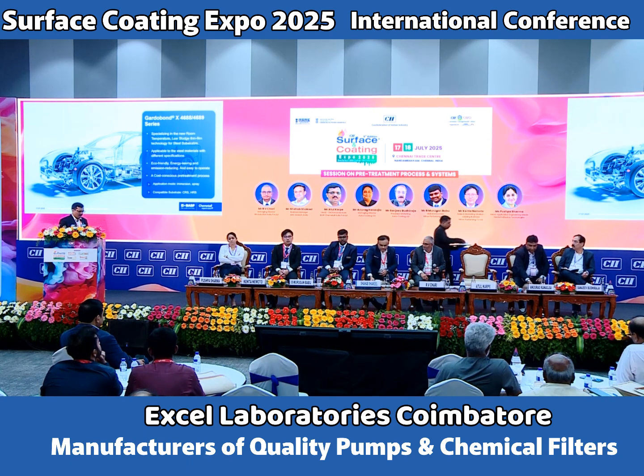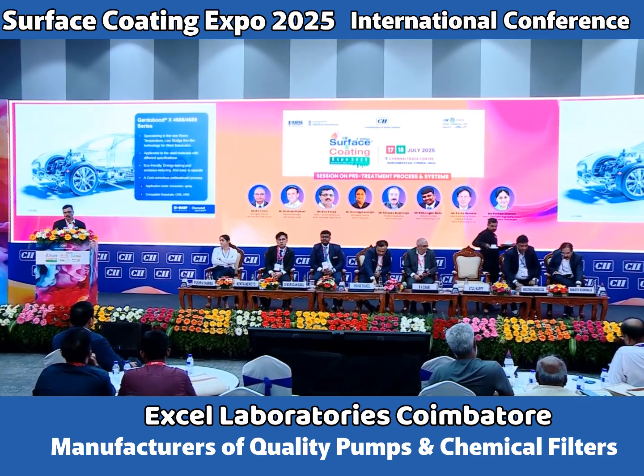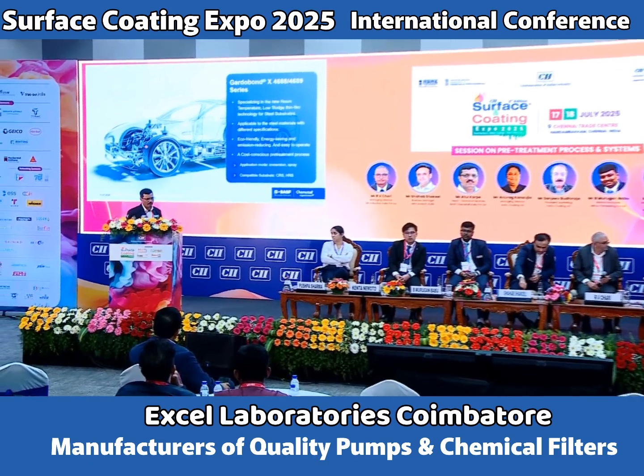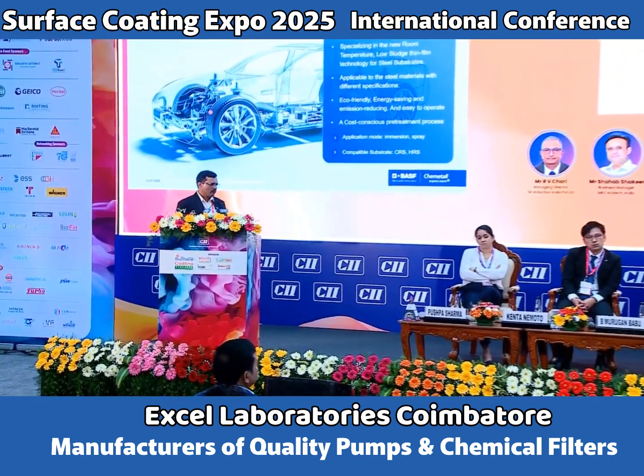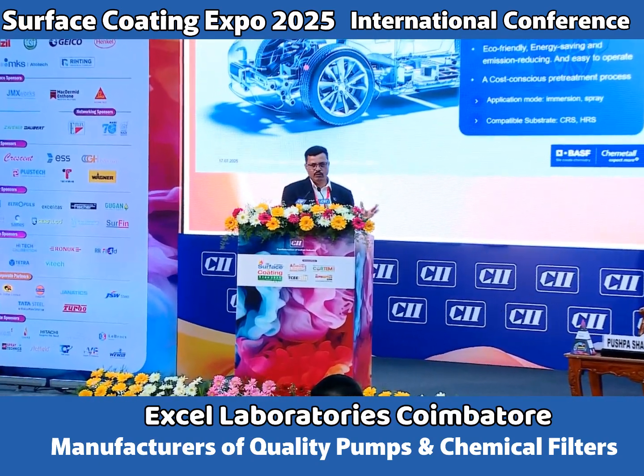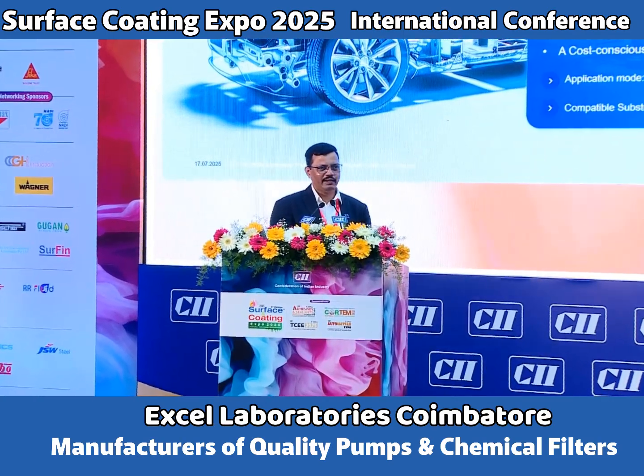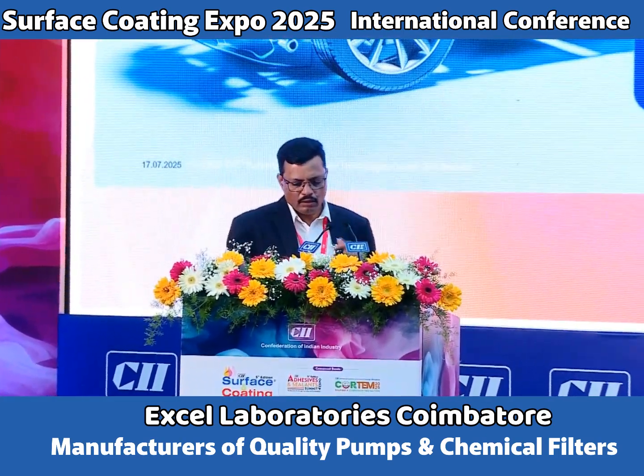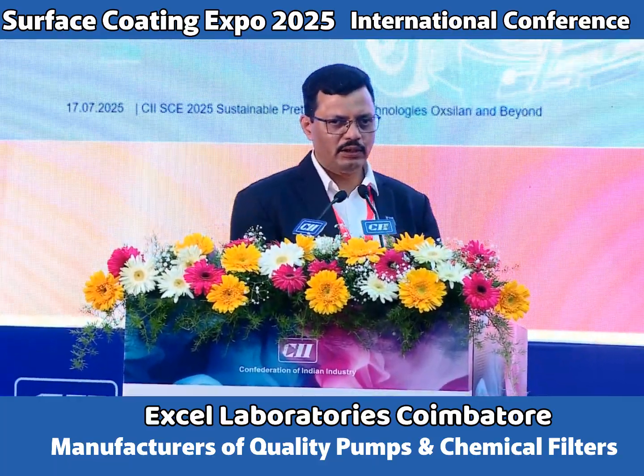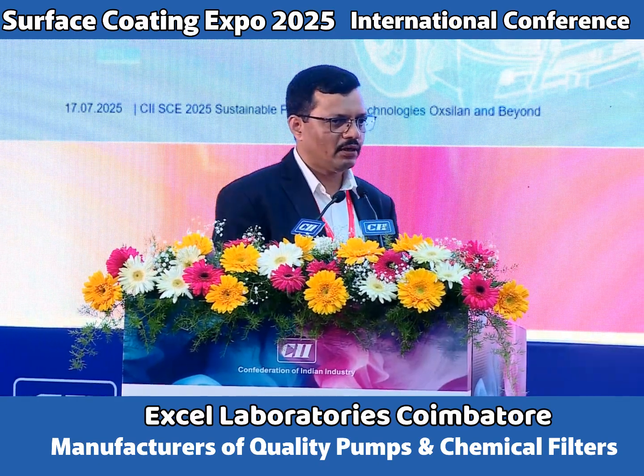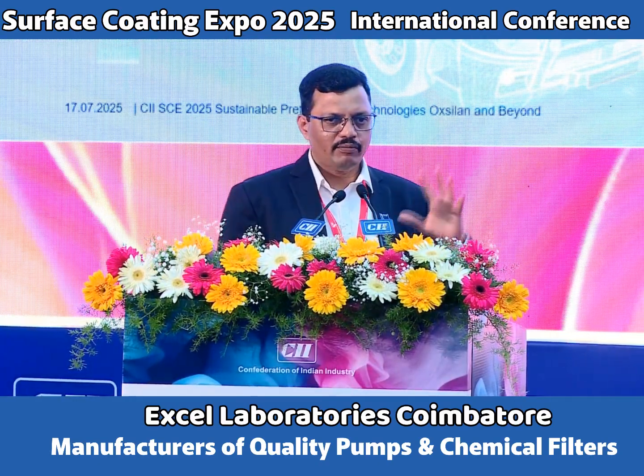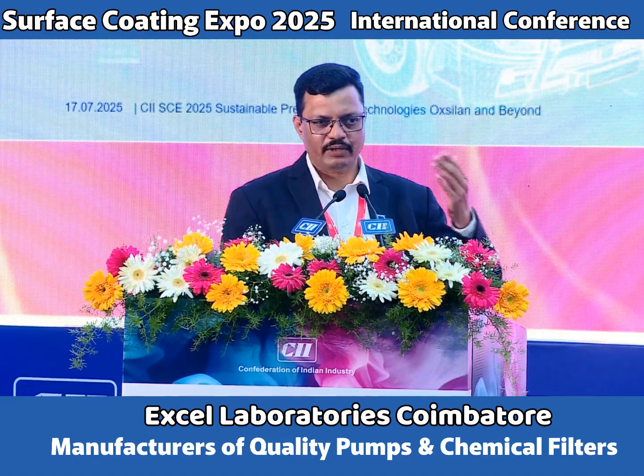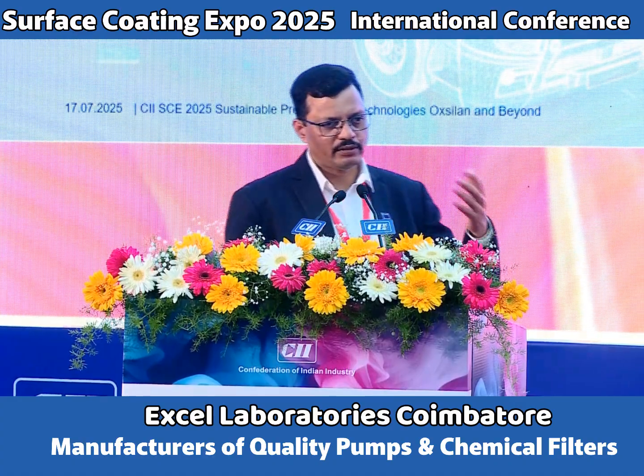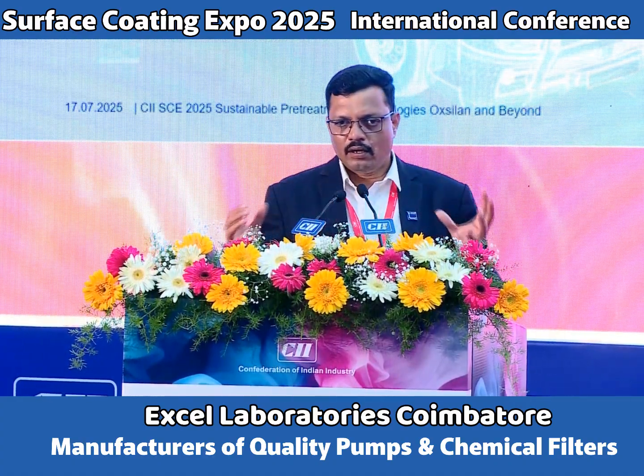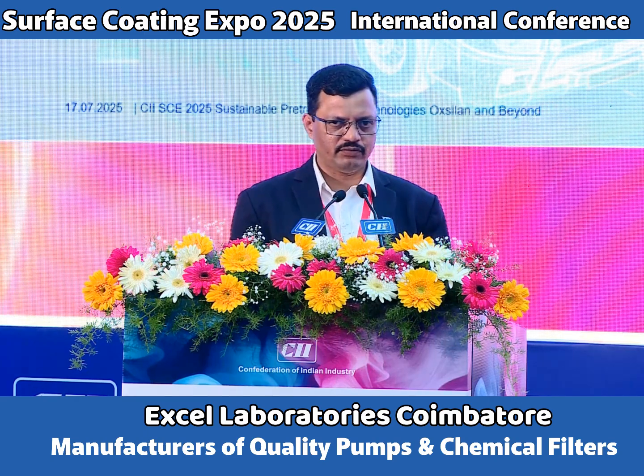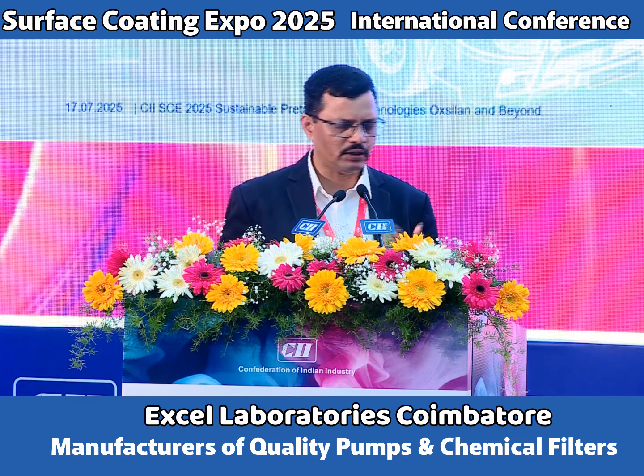So, as I said at the beginning, we are evolving more and more into these thin film technologies, and this is one of the products which is specifically made for giving better corrosion performance on cold rolled steel or difficult-to-treat steels like HSS or boron steel material. Most of the advantages of this process are similar to the Oxsilan thin film technology, and the reaction mechanism is also the same. Here we have a different type of novel polymer being used. The steps, as I mentioned earlier, are the etching of the metal, then the formation of the zirconia matrix, and then deposition of the new functional polymer, which gives better performance on cold rolled steel surfaces.